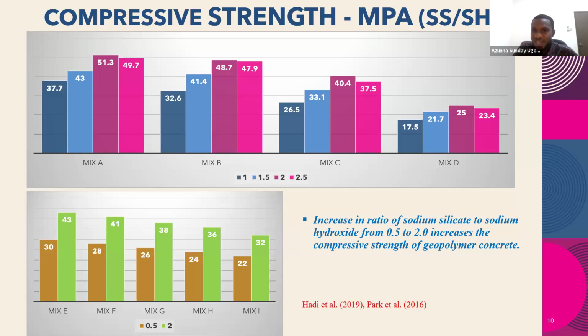Then, after it solidifies, you need your sodium silicate to densify your concrete. So the ratio between your sodium silicate and your sodium hydroxide, you have to be able to strike a balance such that the binders in your geopolymer have enough sodium hydroxide to work with to give you the strength that you deserve. And the sodium silicate is enough to bond your entire concrete. The geopolymer matrix or the geopolymer paste and your fine aggregate and your coarse aggregate are effectively bonded with the content of your sodium silicate.